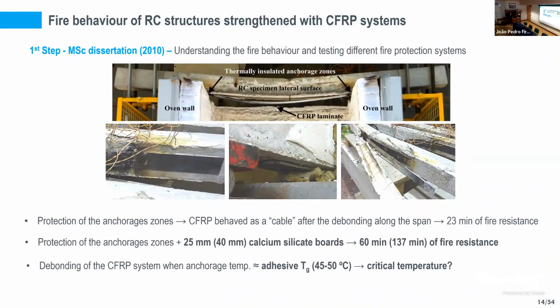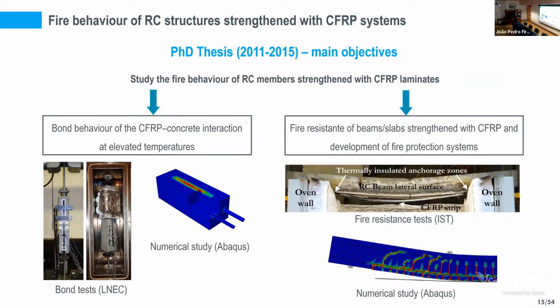of fire resistance, which, by the way, is not enough for typical building requirements, but we also confirmed that by combining the insulation of the anchorage zones with additional insulation at the central part of the system, we were able to attain fire resistance times that fulfill typical building applications requirements. And we also concluded that probably the glass transition temperature of the adhesive could be considered as a critical temperature to be used in the design and safety verifications of this system when related to fire safety. So, the first step was my master